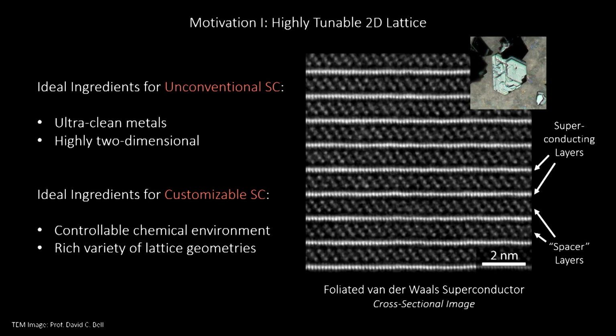It's an excellent question. So yeah, the question is really focusing on the fact that these are layers of superconductors, but there's no superconductor between these layers. And so when we probe these systems, we measure superconducting properties in all directions. So we find the very good metals in plane, they become superconducting, but out of plane, we also can measure supercurrents in some settings. So it's a question about length scales. It's like how long a distance do I have to leave the superconductor before I'm no longer superconducting? So I think that being able to measure these properties out of plane versus in plane gives us insights into these materials, but also shows that they're anisotropic.